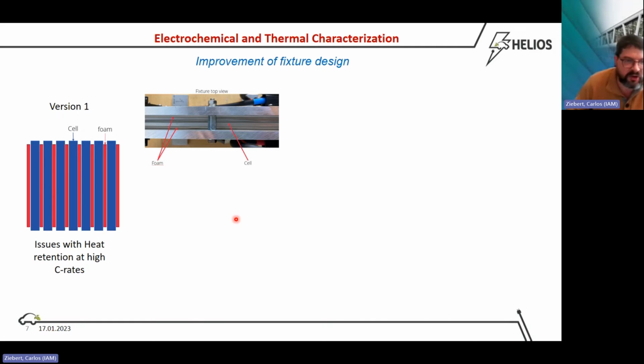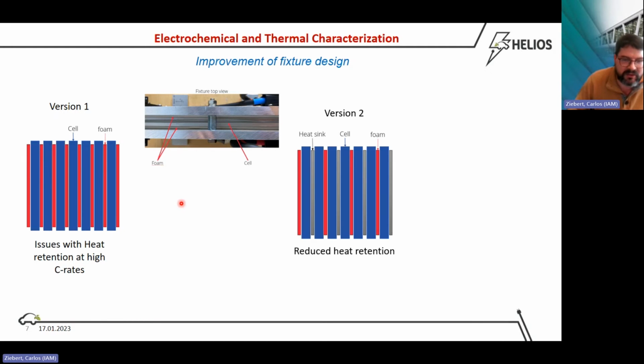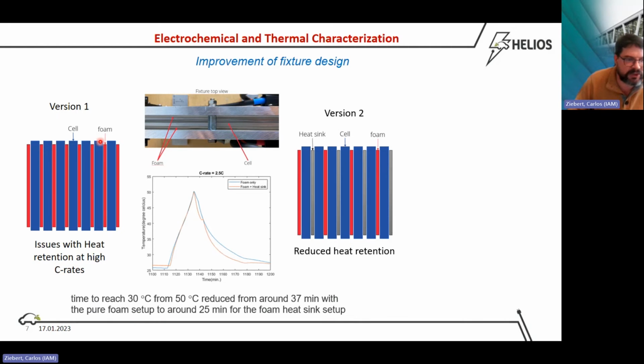Then for the pouch cells, we saw that we had some problems with the fixture design for the cell testing. So first we started here with the cell and the foams which had been proposed by the cell manufacturer, and then we found out that the temperature is increasing too much on the surface of the cells if we are using rates of 2.5 C, which is allowed from the specification of the cells. So we decided to put the heat sink on one side and only the foam on one side, and then we saw that the temperature went down again much faster after such charging at high temperatures.